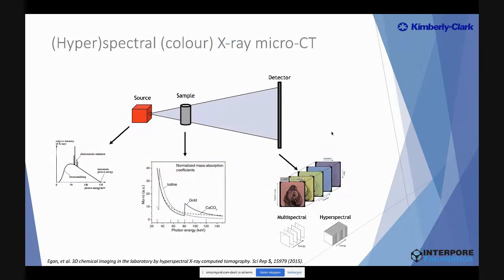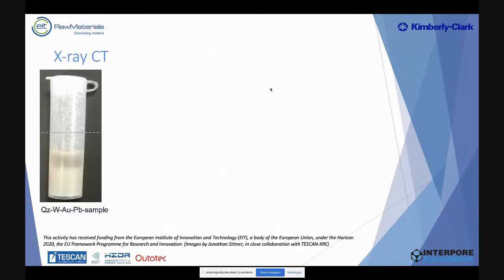Another study that we are working on at the moment is combining X-ray CT with hyperspectral imaging. This is also referred to in the literature as color micro CT. You also just need a source, and you have your sample in between. Then what you do is use a spectroscopic X-ray imaging detector, and those detectors should have sufficient energy resolution to distinguish individual elemental absorption edges. And I will show you what the results could be.